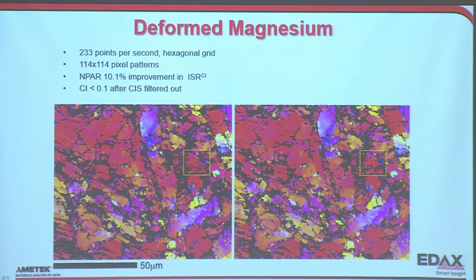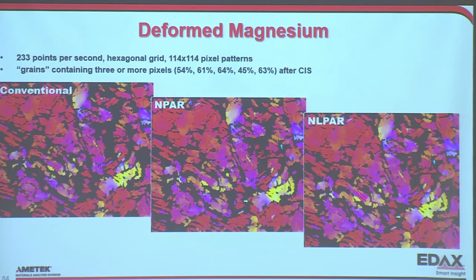Just to show now on a really difficult sample, deformed magnesium for our friends in the back. You can see this is very difficult. So this is after NPAR here, and then this is NLPAR. And you can see, it's 54% indexing rate with conventional, 61 with NPAR, 64 with NLPAR. I'll come back to these. So it does give us a 10% improvement over what we had before, but it's still a difficult sample. We can only do so much.